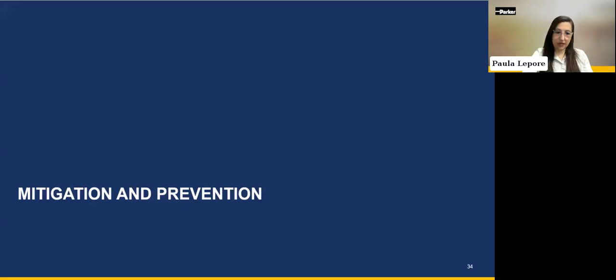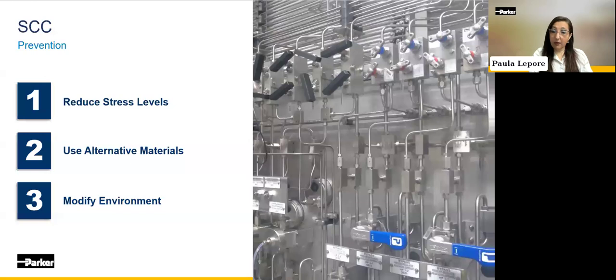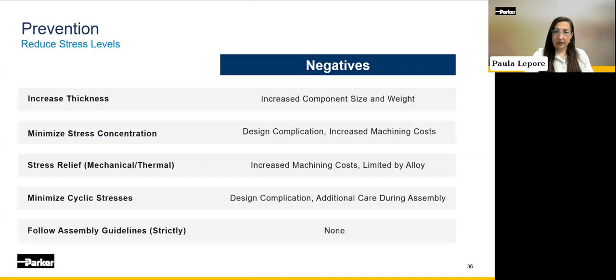Paula? Thank you, Anshul. So let's carry on and go back to the 3 requirements, or prerequisites, that we discussed previously as necessary for stress corrosion cracking and hydrogen embrittlement to set in. We can try to reduce stress, use higher alloys, or try somehow to control the environment, to put it simply. To reduce stress, we can do several things, but they all come at a cost. We can try to increase the material thickness. We can try to minimize stress concentration and cyclic stresses. We can try stress relief, mechanical and thermal, but it all comes at increased costs.